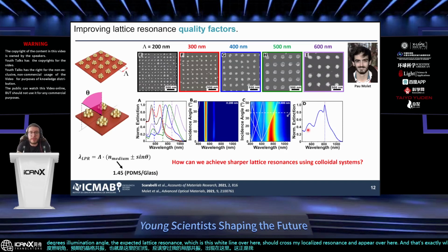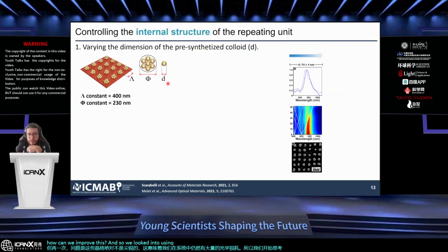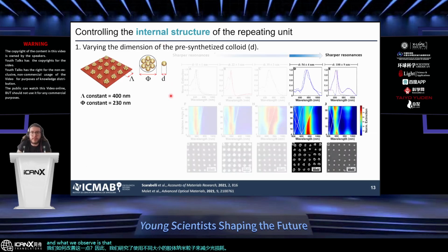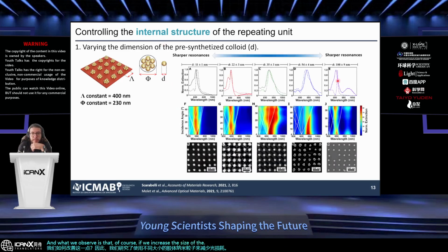But once again, the problem is that these lattice resonances are definitely not sharp, which means that we still have a very big amount of optical losses in the system. And so we started thinking, how can we improve this? We looked into using different size colloidal nanoparticles to reduce optical losses. And what we observe is that, of course, if we increase the size of the particle, we observe much sharper resonances. This is due to the fact that we start having single nanoparticle arrays. But this is very, very complicated to do. The arrays are not very uniform, because placing single nanoparticles using a colloidal templated self-assembly system is not easy, especially over a vast area. But what we observe is that even if we reduce the size of the nanoparticle, we started to observe something extremely sharp.